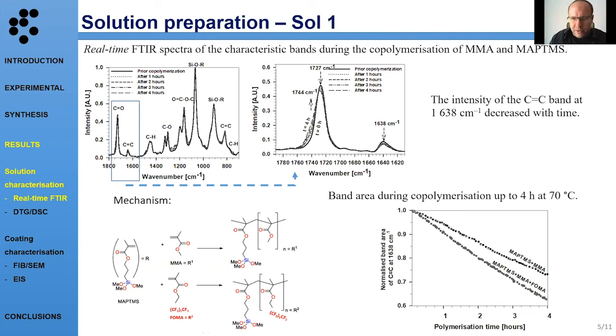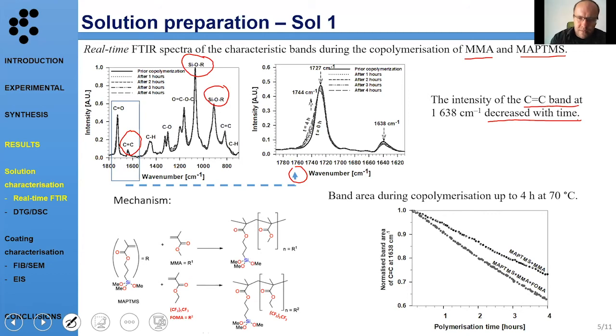Here are the real-time FTIR spectra of the initial methyl methacrylate and the organically modified silicate. When we combine them together, we see that the characteristic bands for methoxy groups are still present in the spectra. But on the other hand, we can see some differences in the bands related to double bonds. If we take a closer look, we can see that the intensity of the double bond band decreases with copolymerization time. So if we wait, for example, 4 hours, the band intensity decreases. The reason is that the acrylate groups react together and form a network in our first solution. If we look more closely, we can see that this process is quite linear.